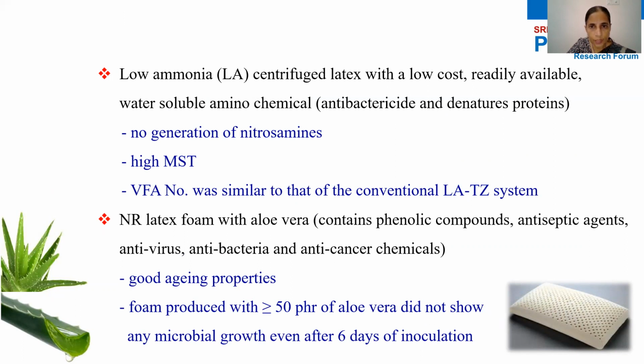Low ammonia centrifuge latex was prepared with a novel, low-cost, readily available water-soluble amino chemical. This amino chemical can act as a bactericide and has the ability to denature proteins. No generation of nitrosamines was found, and the MST of the latex was at a high level. VFA number was similar to that of the conventional low ammonia TMTD zinc oxide system.